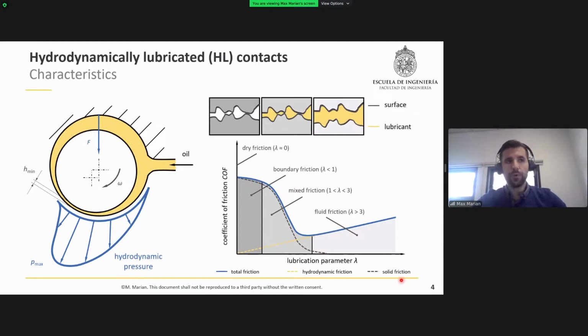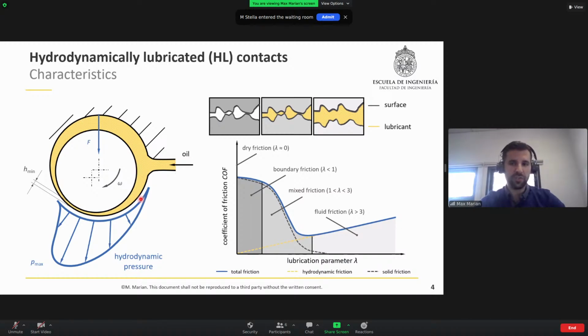The use of lubricant, of course, is an effective way, both in nature and in industrial technology, to reduce friction and wear in highly stressed tribological contacts due to the partial or the complete separation of the contacting partners by an intermediate medium, the lubricant, which generally has a lower shear resistance. And the formation of a separating hydrodynamic fluid film depends on the gap geometry, the relative movement of the contacting surfaces, the viscosity of the lubricant, and also the adhesion conditions.